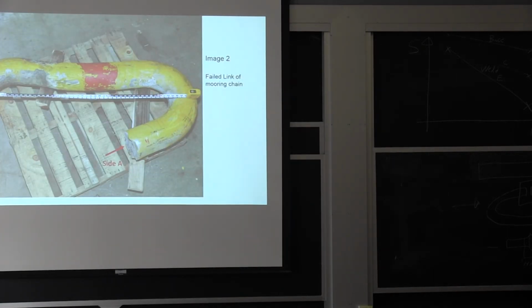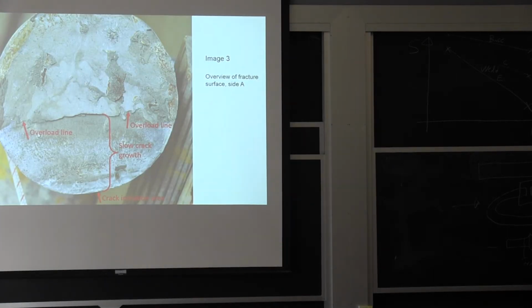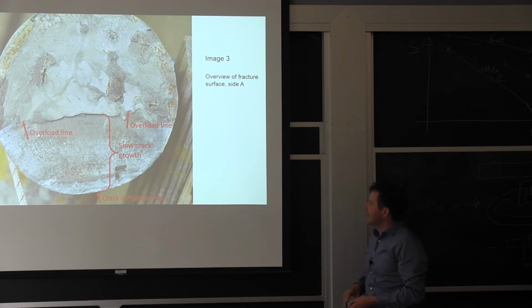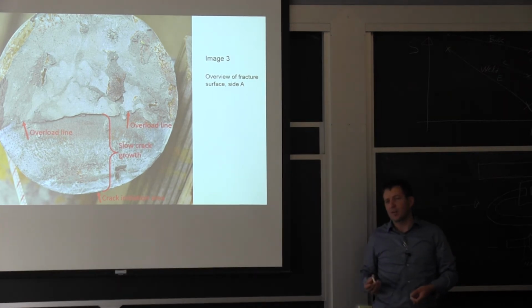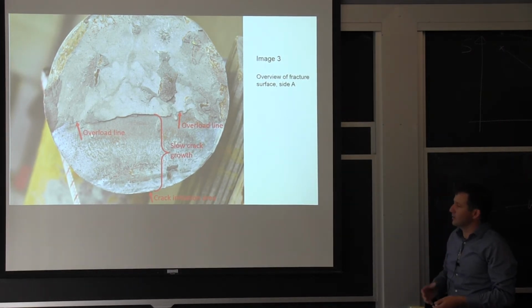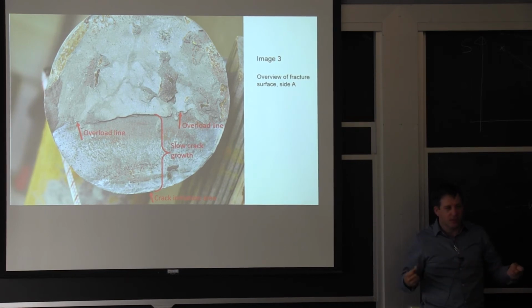So it just failed on one side. If we're looking at it after the fact, this is pretty much the weld joint, and you can see on top, it's not all that great. It almost looks like a brazing joint, right? It's really flat, and you have some zones that are a little bit shiny. You have all sorts of things, but it's not a really rough surface that you'd like to get when you have steel with high ductility. It's not a tear, it's just really a fracture, a straight fracture across the surface.